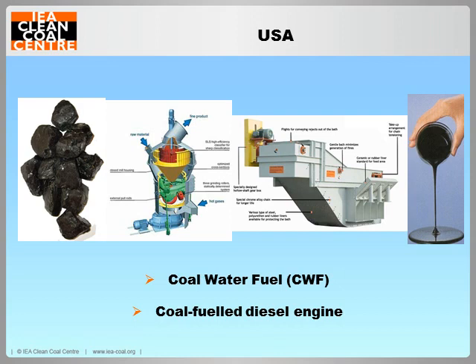The minerals can be washed or beneficiated using physical and chemical beneficiation methods. At the time, physical washing could produce coal water fuels with 2 to 3% ash, and the chemical beneficiation could produce coal water fuels with less than 0.5% of ash. But the chemical beneficiation methods are generally more expensive. With all coal water fuels, additives can be used to control viscosity and stability. To further minimise wear, an adapted diesel engine was developed that uses harder engine materials and a purpose-built fuel injector.